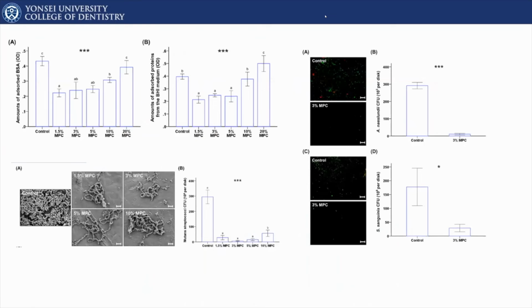But with the amount of protein absorption, it was very evident that the previous studies were being confirmed. At 1.5 to 5% of the MPC, the amount of absorbed BSA, the bovine serum albumin, is dramatically reduced, as well as the proteins from the BHI medium. The interesting thing was that increasing MPC actually did not prevent the absorption further. It actually went back to the normal control, so it actually increases the absorbed BSA. Perhaps the reason is that the interaction between the MPC molecules and the surrounding matrix is preventing the MPC from being active in terms of exposure to the surfaces. But certainly it has an effect in terms of antibacterial properties.